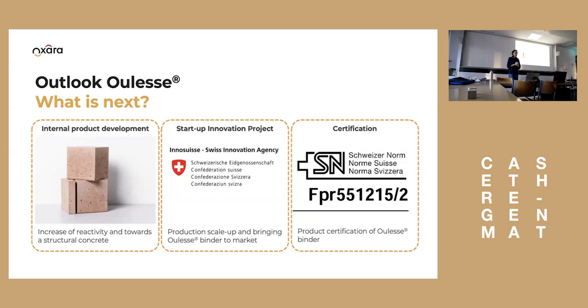Then we got a grant from Innosuisse for a startup innovation project, where it's about the production scale-up of this binder and bringing it to market. And we are working on the certification to get this binder certified. Currently in Switzerland, for binders to be certified, there is a minimum amount of cement that you still need to introduce into your binder. Ours doesn't have cement clinker in it, so we need to find a way to certify this binder, which would open doors to be able to use it according to the norms.